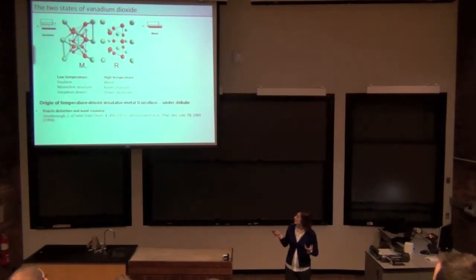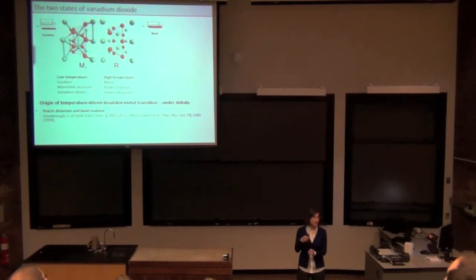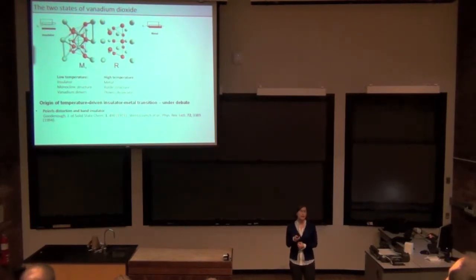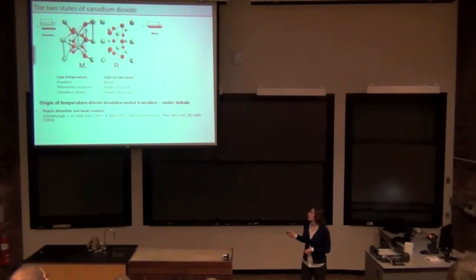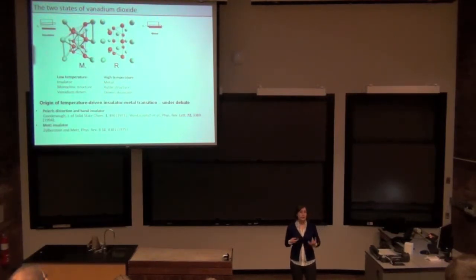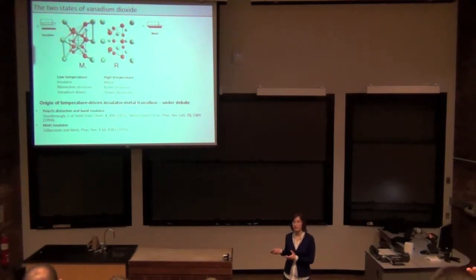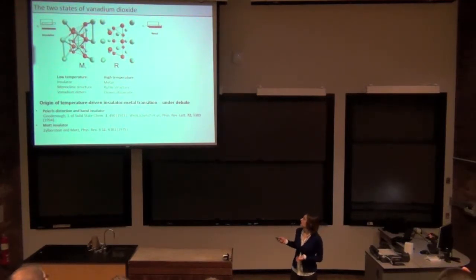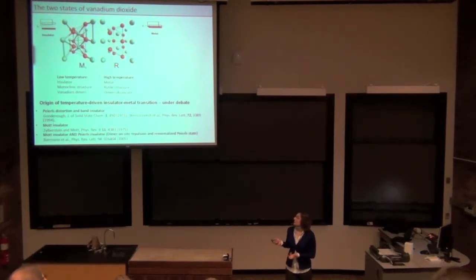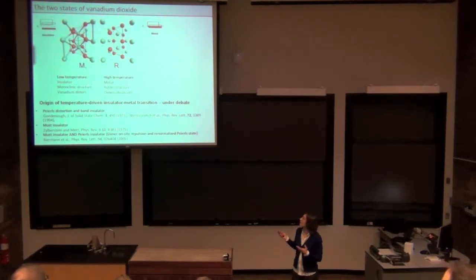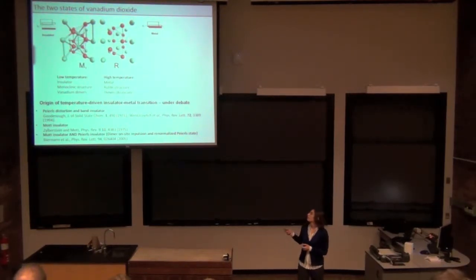So some people are, of course, immediately looking at it and saying, okay, you have some sort of dimerization. That is a signature of the Peierls distortion, so it must be this band insulator, a Peierls insulating state. Other people are saying, no, to actually get this kind of insulating behavior, you need to consider electron-electron interaction, so it's actually many-body effects, it's a Mott insulator. Then, relatively recently, in 2005, another theoretical paper came out and said, well, you're both right. You actually need both. You need the dimers, and you need to consider many-body effects to get this